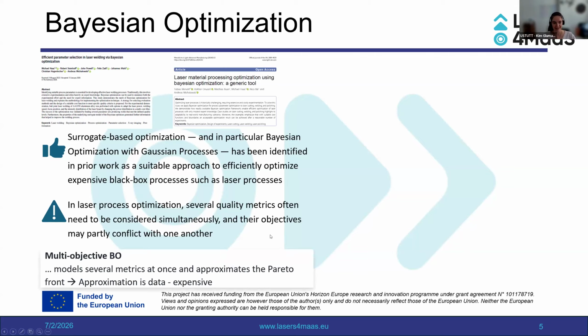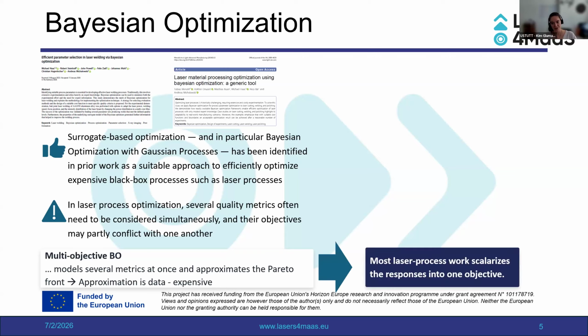And one approach to tackle that is multi-objective Bayesian optimization. This one models several metrics at once. So it has one model for, let's assume, welding depth, one model for spatter, and so on. And then we can approximate the Pareto front and decide individually which set of parameters gives us the best compromise in order to have a certain welding depth, a certain productivity, and the least amount of spatter. But the approximation is data expensive, and thereby we lose a bit of the advantage the Bayesian optimizer normally gives us.